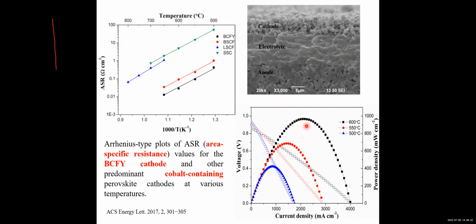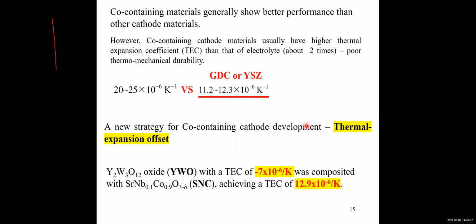Actually, we also developed a few other perovskite materials, and based on our experience, we found normally the cobalt-containing materials show much better performance than other materials. However, there is a problem for cobalt-containing perovskite materials, because normally their thermal expansion coefficient (TEC) is high.